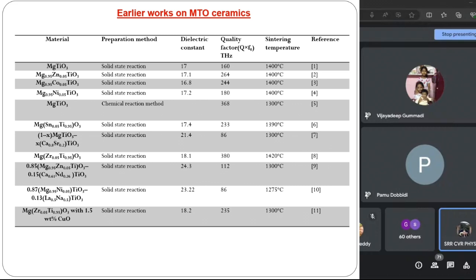But if you look at it, the sintering temperature is above 1400 degrees C, which is very difficult. But there is another technology called LTCC, low temperature co-fired ceramics. Low temperature co-fired ceramics means you will have a ceramic and then a low melting point metal, for example silver. Silver melting point is about 960 degrees C. So if I have silver with the material, it needs to be fired. Co-fired means metal and ceramic we will fire together. That's where we call them low temperature co-fired ceramics. You have high temperature co-fired ceramics also. In the case of high temperature co-fired ceramics, we use noble metals, gold, platinum, like that, because they go to higher temperature. If you do the material technology at low temperature, LTCC, it is more efficient.